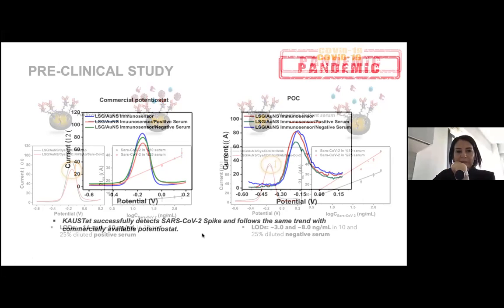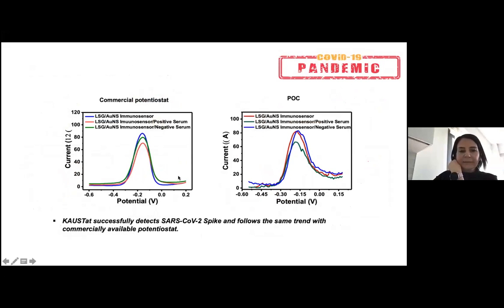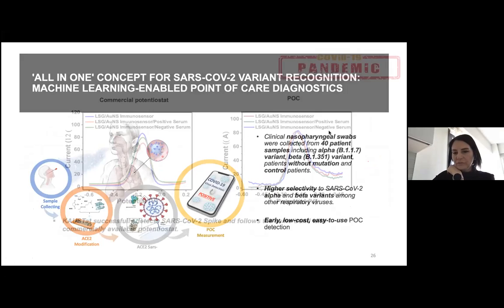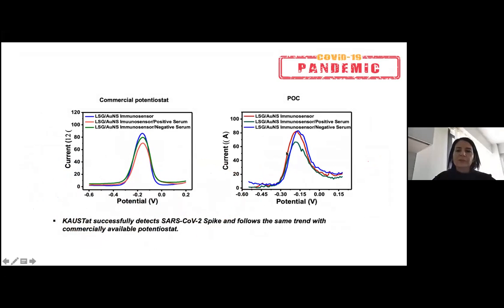So at the final step, we are trying to validate the POC system, and we compared it with a commercial potentiostat, PalmSens potentiostat. Of course, there are some noises. No correction was made directly. We put our data, so we can see the same trends. And with the redox probe, in the case of negative samples and positive samples, we obtain the same trends in this signal reduction.